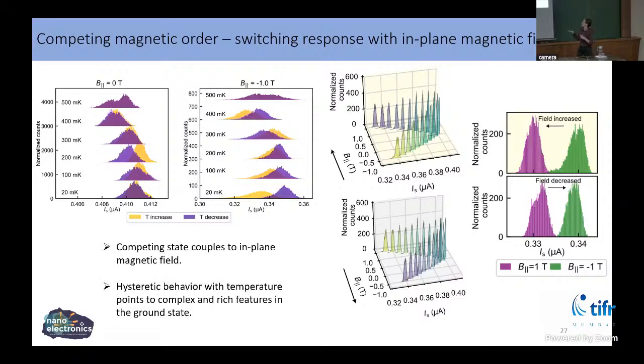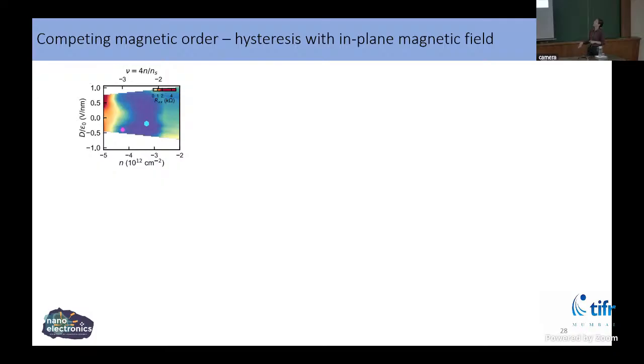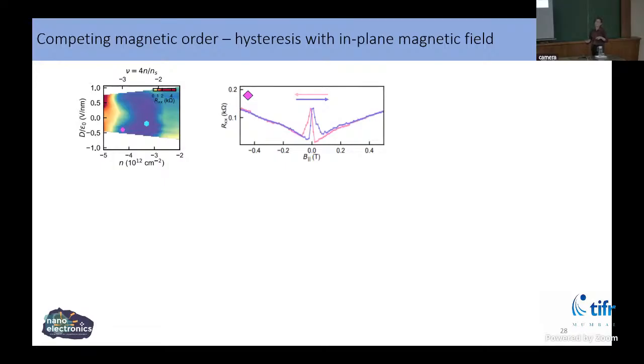So from this, you can infer that obviously something magnetic is going on. There is some intrinsic magnetic order present that is preferring a particular direction of magnetic field. To probe more into this, we looked not only in the superconducting part, but a little bit outside of it, where my device shows some small non-zero resistance. We got this curve, which clearly shows hysteresis features, marking that there is a magnetic order present just right outside the superconducting region. So it's natural to connect the dots and say that I get signatures of magnetic order in the superconducting part and also clear signatures just outside. So the superconducting order is actually competing with the magnetic order.